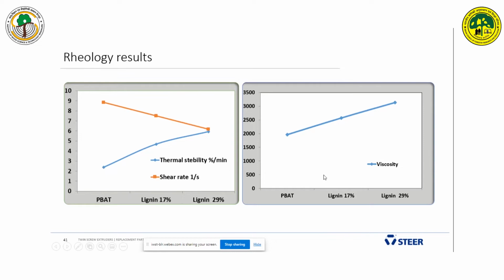And again, the viscosity, obviously the addition of lignin increases the viscosity. If you compare with any mineral filler, with the addition of calcium carbonate and other fillers, when the viscosity increases, there is an increase in the shear rate. But in the case of lignin, it's the reverse.